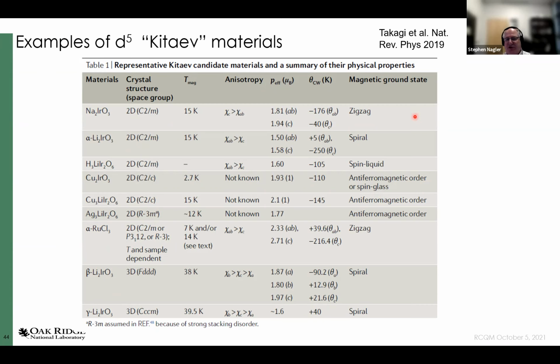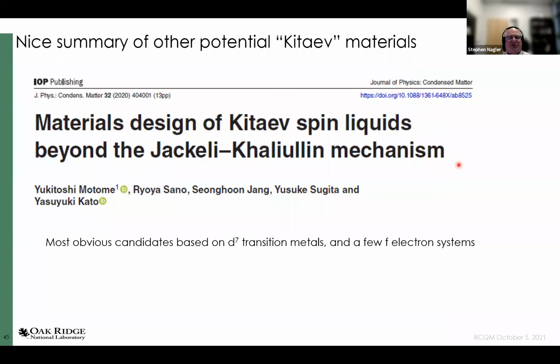Now, every single one of these orders in some fashion, at least in zero field, at a low enough temperature. A lot of them tend to order in the zigzag phase. Some, well, every single one except one that I'll mention. Others are antiferromagnetic, etc. The one outlier here is this protonated lithium iridate, which it says here spin liquid, but this has a complication that there's disorder in the system, which actually can have a significant effect. Anyway, I'm going to now specialize shortly to alpha ruthenium trichloride.